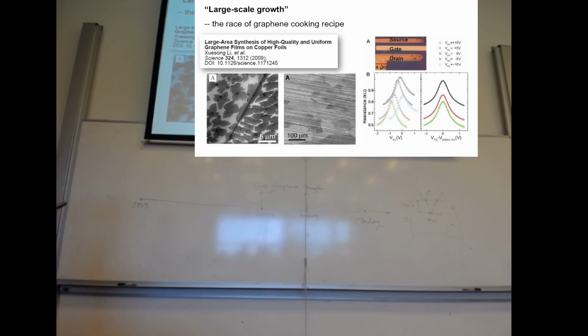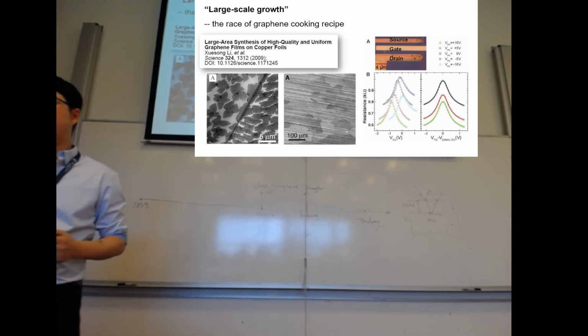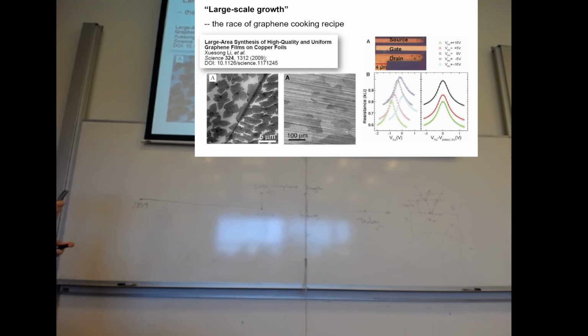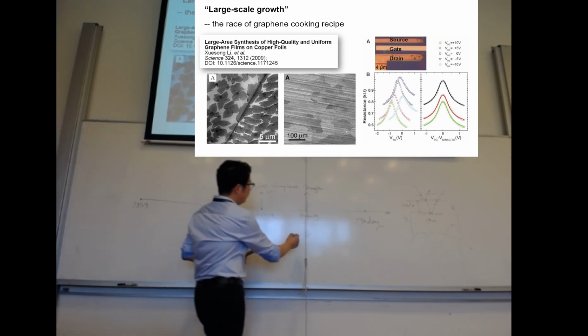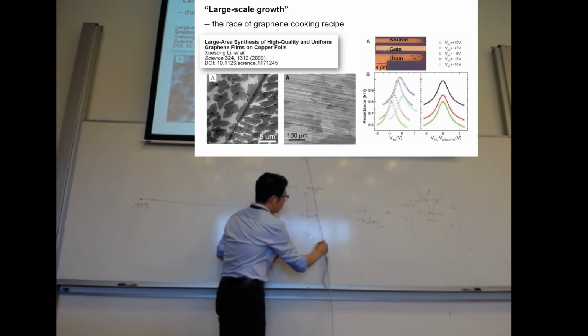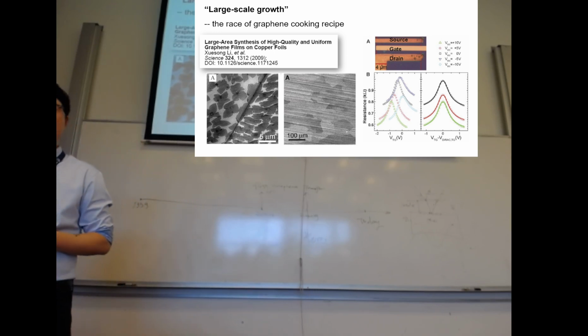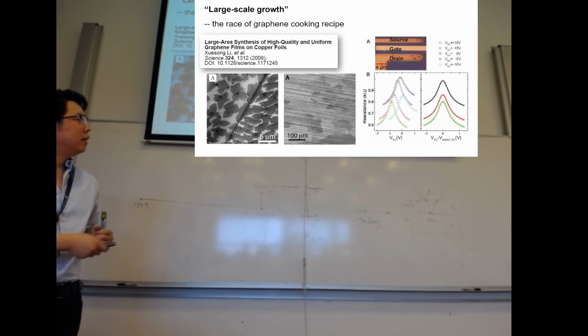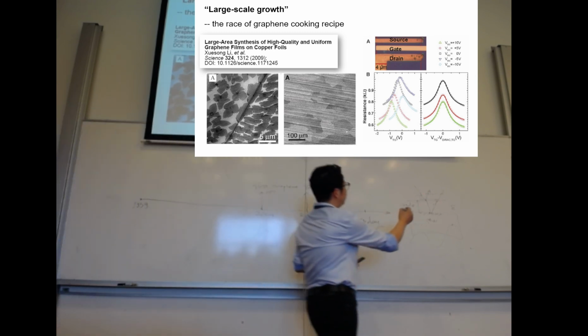And then once you do that, you can also have source, drain and gate patterned by standard lithography methods. Then you will have this graphene transistor, exactly like Geim and Novoselov were doing in 2004 using the exfoliation method. And they also have very good mobility at room temperature, about a few thousand. So this makes people very excited, because before you could only exfoliate very small flakes in labs. Now we can grow them on a large scale, and that's a big breakthrough at that time. Let's say CVD transistors. When we say FET, it means field effect transistor. It's a gate, oxide, and semiconducting channel, like the one shown there, with just the source and drain there.